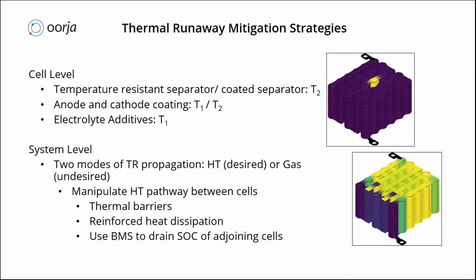And hence, in that case, we need to understand what kind of system level modifications we can make in order to get thermal runaway prevention. So here in this case, we can add certain thermal barriers. For example, you can have thermal pads inserted in your pack, or microchannel cooling plates can be introduced, so that it will take away the heat from the pack, and it will ensure that even though one cell gets into thermal runaway, the thermal runaway doesn't get propagated further.